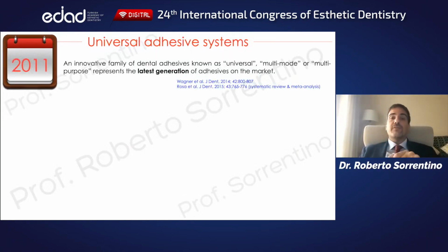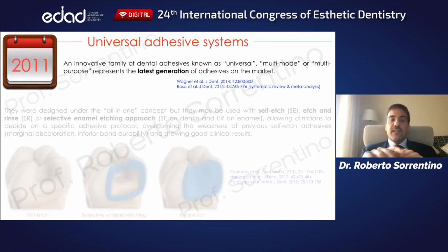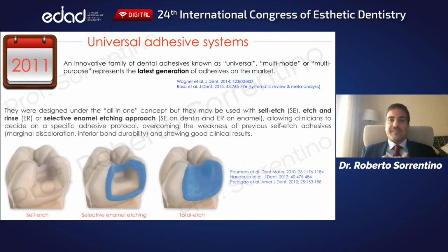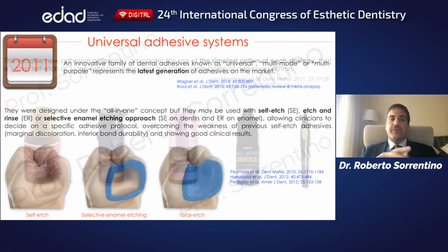Recently, in 2011, a new class of dental adhesives was introduced to the market: the universal or multimode agents, designed as all-in-one systems but with the innovation of being used with etch and rinse, self-etch, or selective enamel etching techniques—very versatile and overcoming the drawbacks of previous self-etch adhesives, like inferior bond durability and marginal discoloration. As a consequence, practitioners can decide on a specific adhesive protocol according to the specific clinical conditions, adopting the simplest solution of each technique.